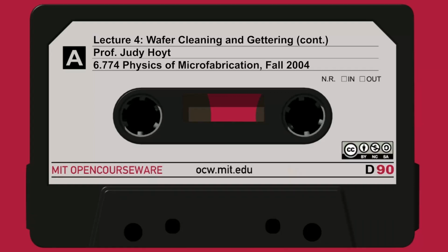Next lecture we'll talk about total X-ray fluorescence. It's a metrology technique that can scan across the wafer, in certain areas, like 1 centimeter spots, and it can measure by X-ray fluorescence the atomic density of certain contaminants on the wafer. And these 5 points, center, top, right, left, and bottom, were taken, and they correspond to these XY coordinates here.